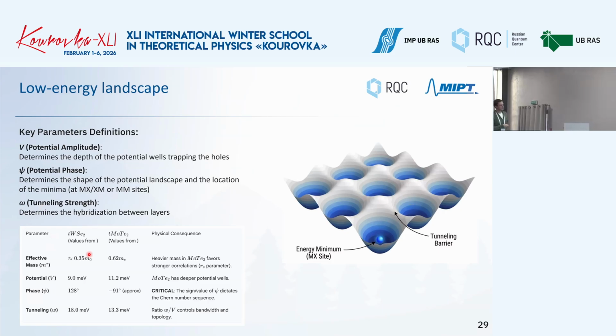And here is the comparison for two types of material, molybdenum telluride (MoTe2) and WSe2. The effective masses are different for these two materials, so then the potential is different. And you see that when you have a heavier mass, it follows stronger correlation, because there are deeper potential wells. And this ratio between this one, it controls bandwidth and topology. So you can play with angles, with materials, and you define what the tunneling barriers and